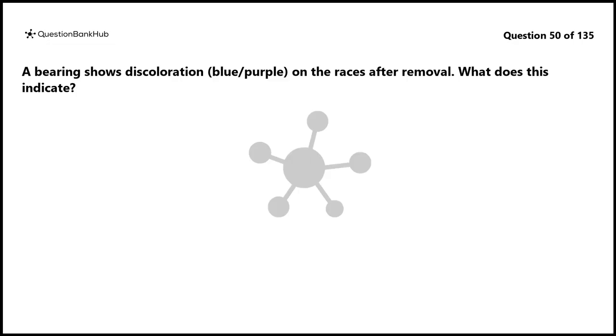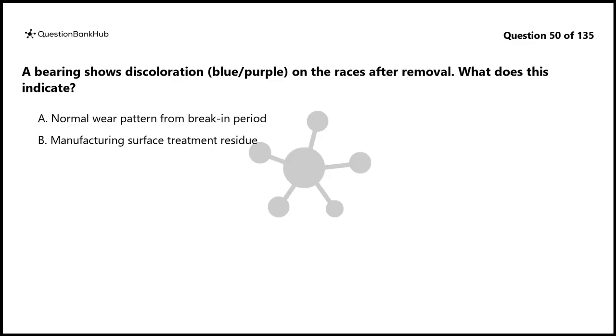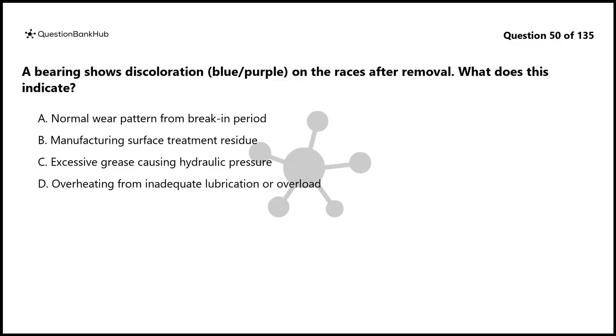Question 50. A bearing shows discoloration, blue over purple, on the races after removal. What does this indicate? A. Normal wear pattern from break-in period. B. Manufacturing surface treatment residue. C. Excessive grease causing hydraulic pressure. D. Overheating from inadequate lubrication or overload.